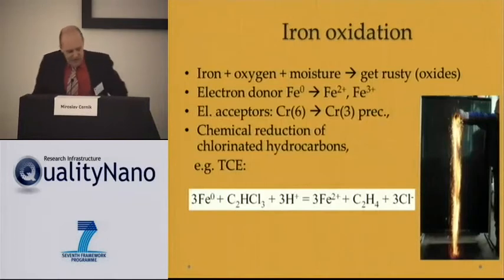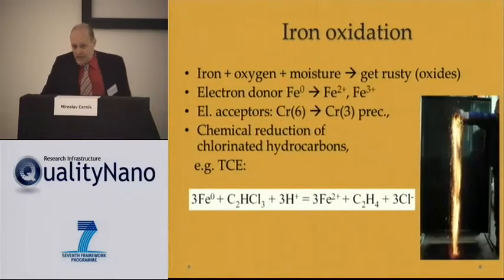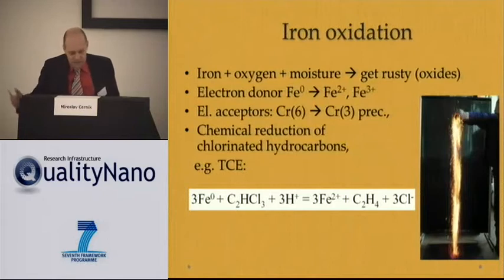So, in general, the reaction is simple. We take the iron, like we have the microscale iron. It reacts with oxygen and moisture and gets rusty, gets oxidized, so in general it's a donor of electrons, and we have some electron acceptors, which can be oxygen, or in our case, it can be some contaminants like chromium-6. Chromium-6 is chemically reduced to chromium-3, which precipitates, and water is clean.